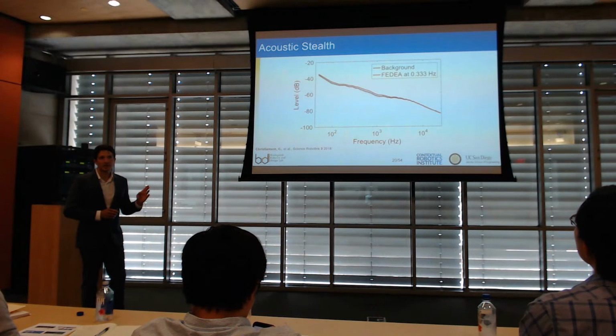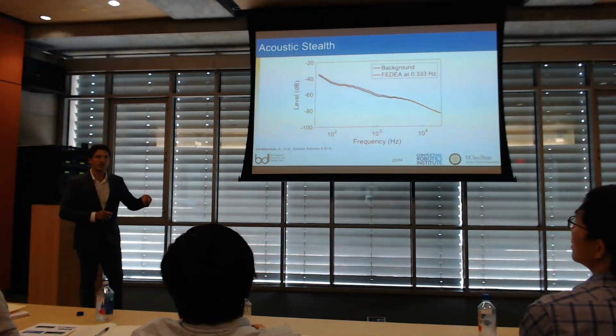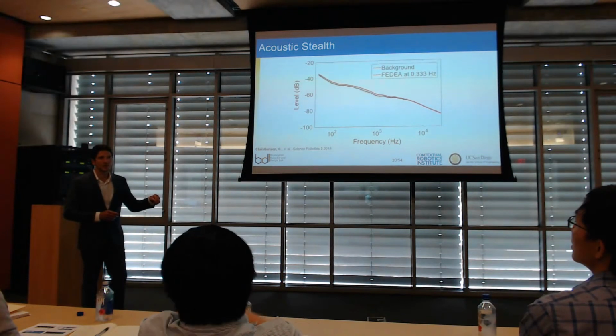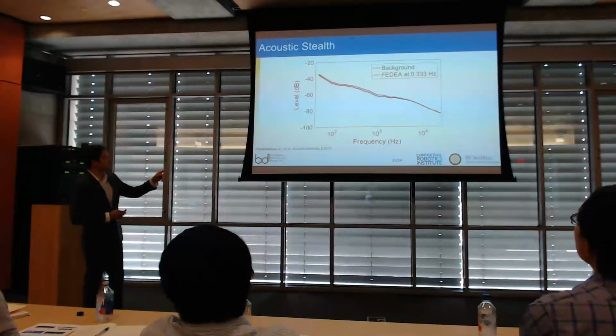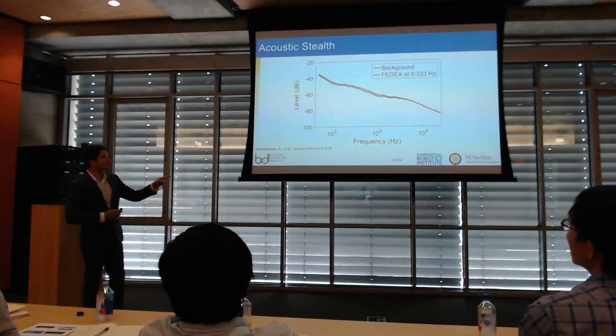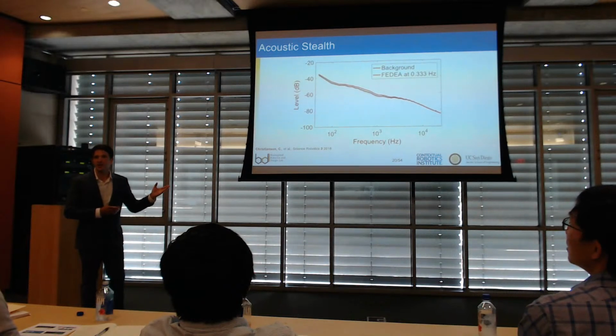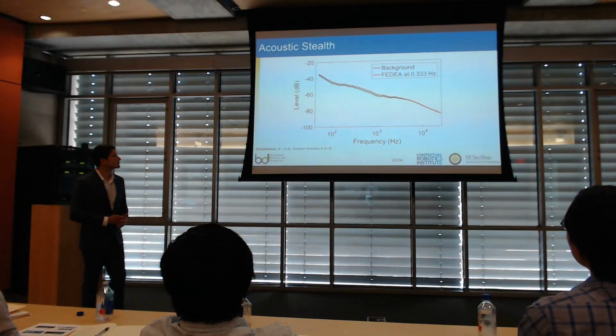I said that we can make it silent, so we put a hydrophone in the water next to the actuator and compared the signal when it was on versus when it was off. And the level as a function of the frequency over the audible range shows that you basically can't hear the actuator, so it's completely silent.